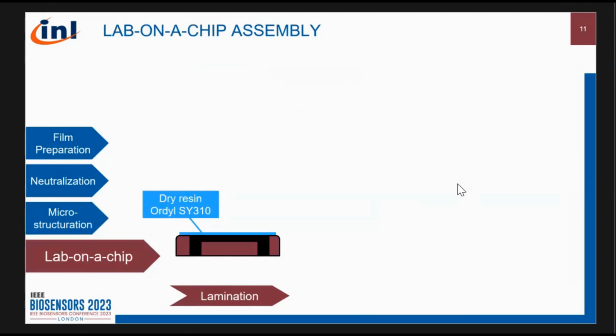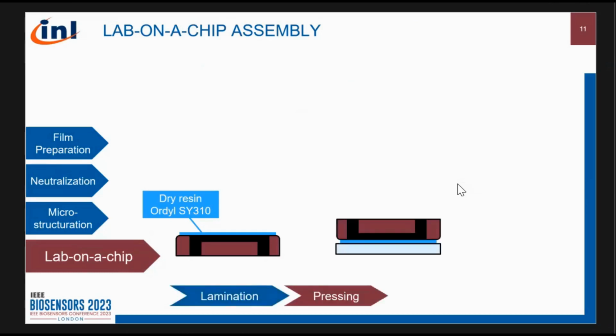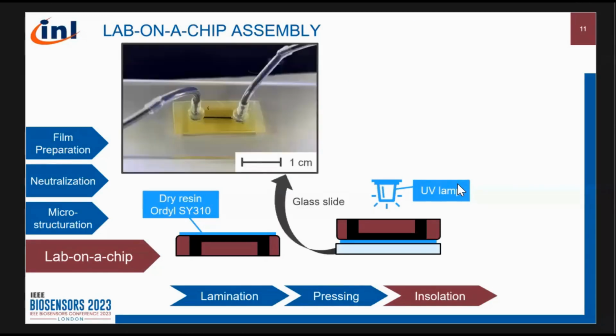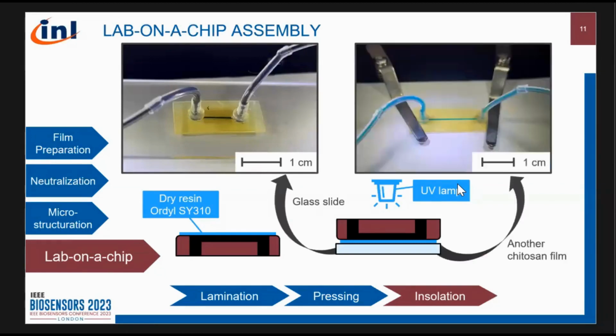And now we still need to seal the device. So we choose to use a dry resin that we laminate on top of the Chitosan film. Then we press it on another substrate to bond it. And we insolate the resin with a UV lamp to cross-link the resin and fix the system. So we managed to bond the Chitosan film to either a glass slide or another Chitosan film. And we verified the water tightness of the system by injecting aqueous solutions that are colored with a food dye on both of the systems.